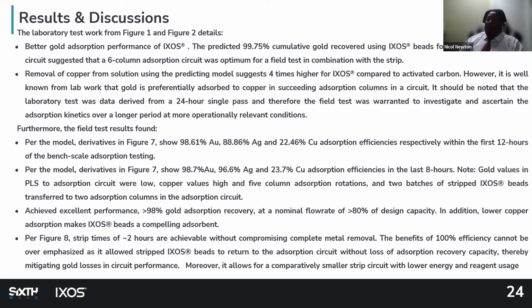It should be noted that the laboratory test data was derived from a 24-hour single pass, and therefore the field test was warranted to investigate and ascertain the adsorption kinetics over a longer period at more operationally relevant conditions. And that is what we did on the field. Furthermore, the field test results also found that per the model, derivatives in figure 7 show 98.61% gold recovered, 88.6% silver, and 22.46% copper adsorption efficiencies, respectively, within the first 12 hours of the bench scale adsorption. Similar results showed for the last 8 hours.